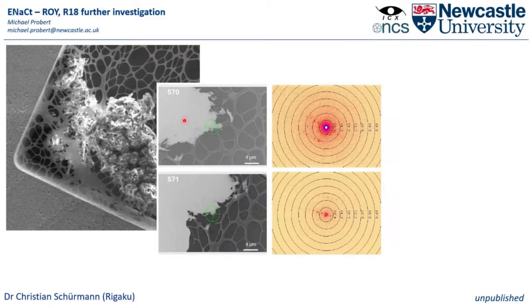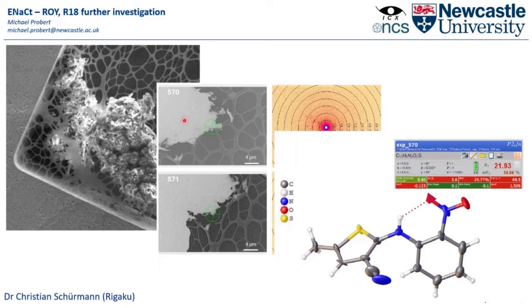And micro-ED allows us to do analysis of those small rod-like crystals, which you would never be able to analyze by single crystal X-ray diffraction, and does give a solution, although does suffer from some of the problems that micro-ED generally has at the moment, which is higher than we like to work with R factors, so ones that are not so common for X-ray diffraction, but is clearly showing us the material and actually giving us a strong indication of what that system transforms into.